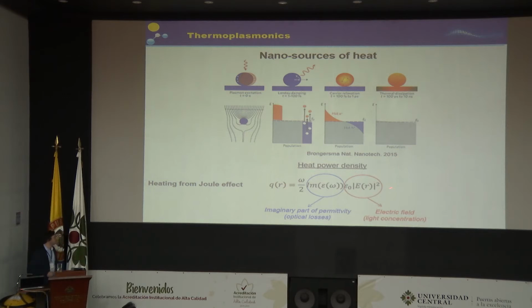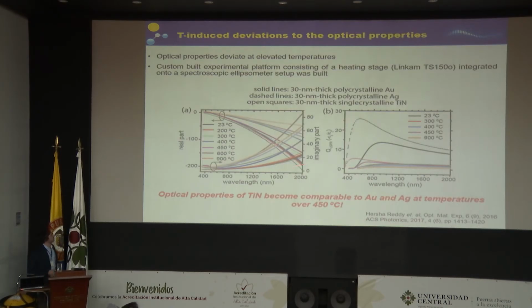This heating comes from the Joule effect. And so what we have to consider to understand how much heat we produce in the material is the electric field inside the materials and the optical losses, so the imaginary part of the permittivity of our materials. And here it's interesting, a series of studies has been published in the last 3 years where optical properties of different materials have been studied as a function of temperature. If you calculate analytically the figure of merit of silver, gold, versus titanium nitride, you can really see that above 400 degrees C, the figure of merit becomes equal.